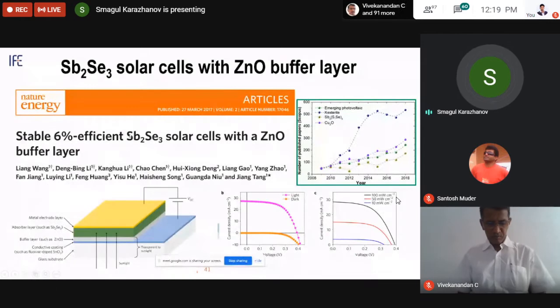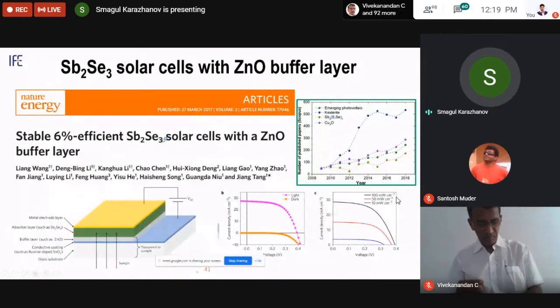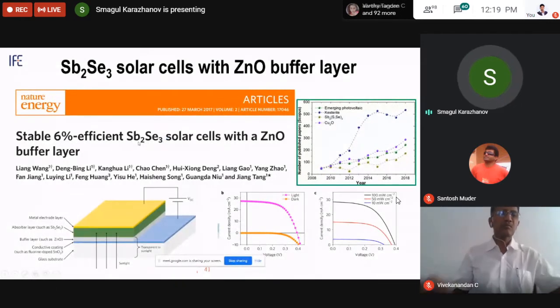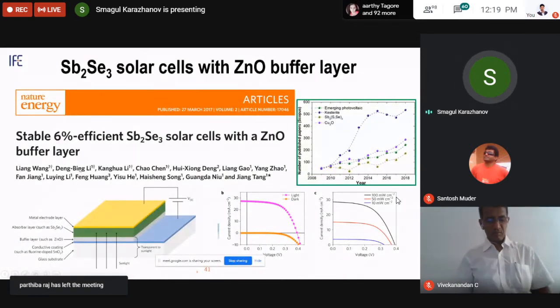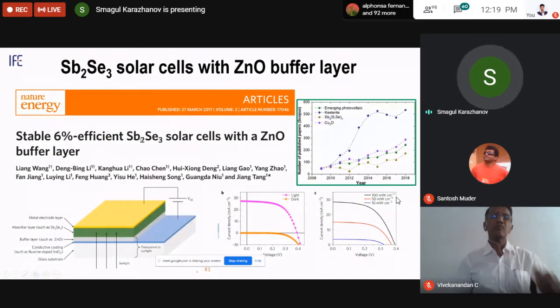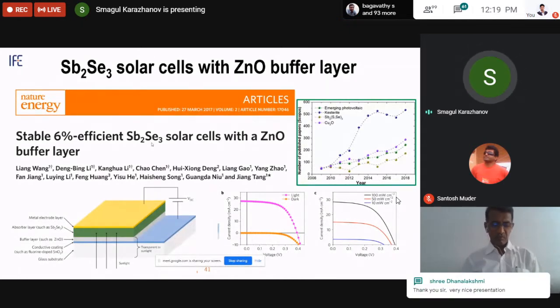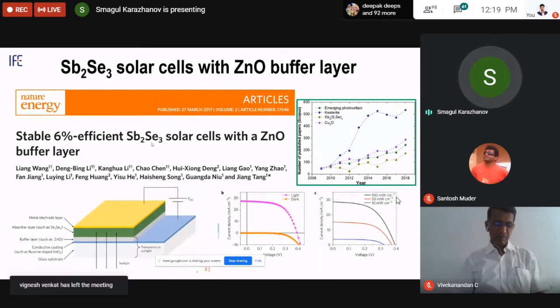But there is one big challenge related to this type of solar cell. It is how to control electrical conductivity. The lower efficiency, around 6 to 10%, is obtained because electrical conductivity of antimony selenide is not controlled at all. But how to control it? This is an open challenge right now. And right now, the community is using insulating antimony selenide. In cadmium telluride, CIGS, CZTS, they are using a simple technique to control cation vacancy.